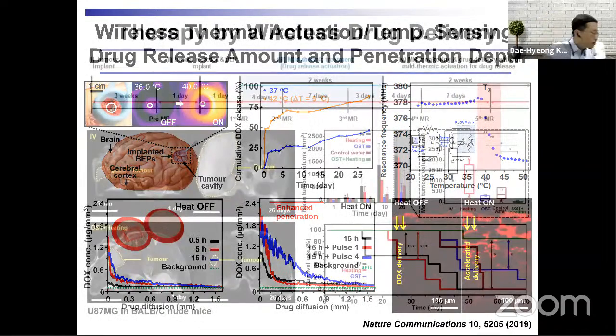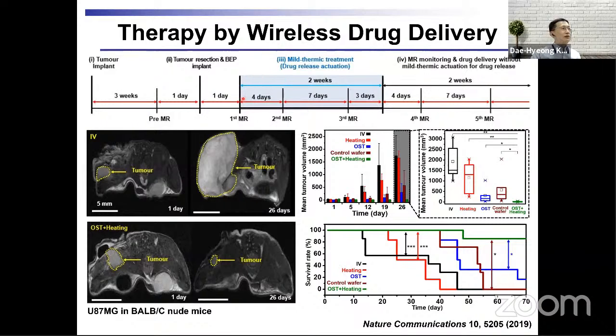And we apply this system to an animal model. We first grow the GBM cells. We use the U87MG cell line, a GBM cell line, in a nude mouse, an immune-deficient mouse. And after cell growth, tumor growth, we surgically remove the core part of the tumor and implant the device in the cavity. And for 2 weeks, we applied 30 minutes of wireless actuation, thermal activation, every 2 days. And after 2 weeks, we just waited for the natural biodegradation of the implanted device. So we waited for natural release of the drug due to the biodegradation.